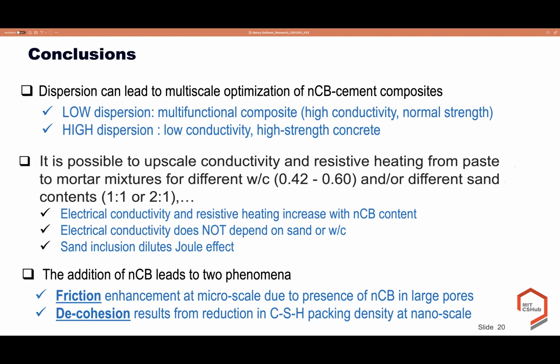While the addition of nanocarbon black also leads to de-cohesion of the material at nanoscale, and this de-cohesion results from a reduction of packing density of calcium silicate hydrate at nanoscale. And this de-cohesion is the reason for the reduction in compressive strength at microscale and the reduction in ductility.